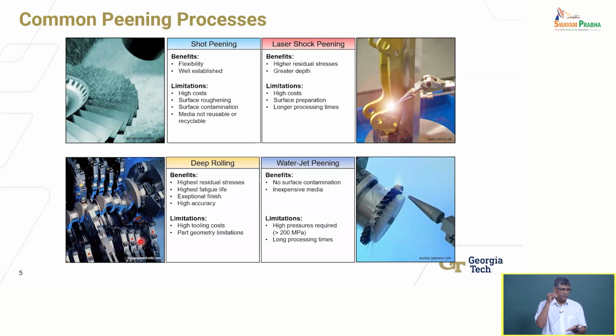So instead of using a mechanical shot, you have a shock wave that actually interacts with the surface, and it's strong enough to plastically deform the near surface region of the metal. So it produces the same end effect. It's just a different way of generating that effect. Obviously, it has its advantages too. Some people use it in the aerospace industry. The one advantage is it can produce residual stresses that are deeper.